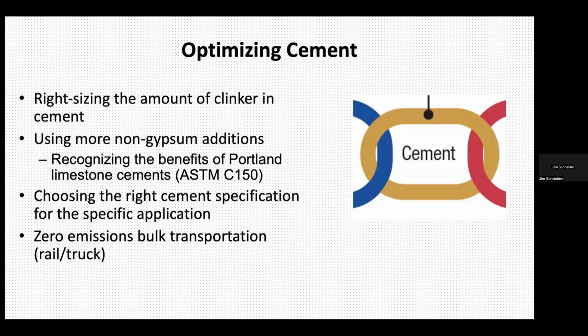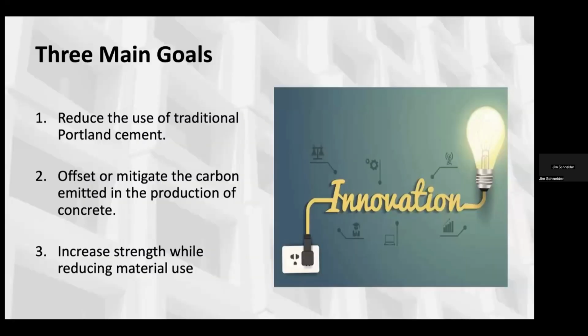So optimizing cement, part of what we want to do as an industry, and this is talking about concrete broadly, is right size the amount of clinker in cement, use more non-gypsum additions, recognizing the benefits of Portland limestone cements, which can really impact the carbon footprint of some of these materials, choosing the right cement specification for specific applications, and then also be thinking about zero emission bulk transportation, whether that's rail, truck. That's part of the equation too. We have to take out the emissions that are coming from that. But it's really coming up with the most efficient methods and materials to make this with. And part of the advantage with precast is that because it is a plant produced material, you really do have that control over the process.